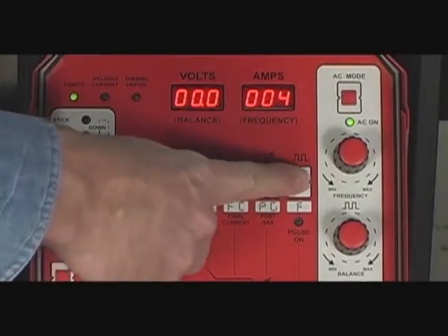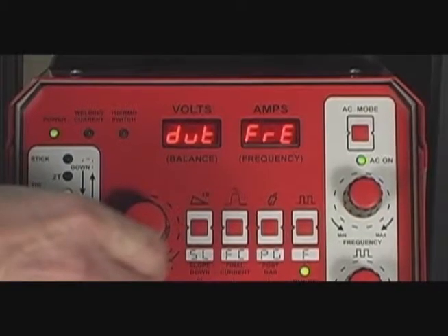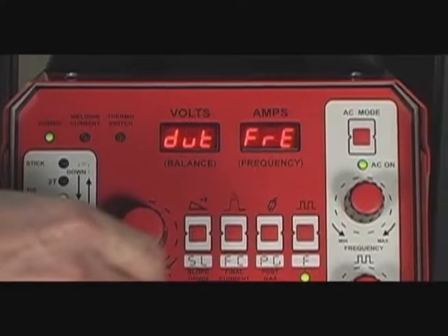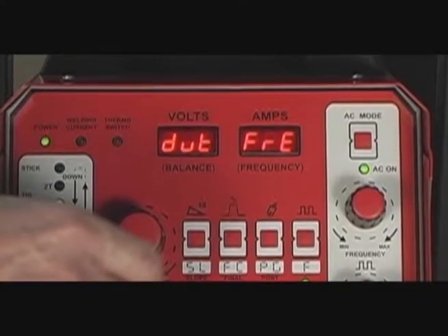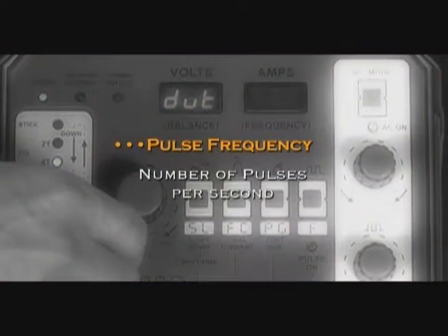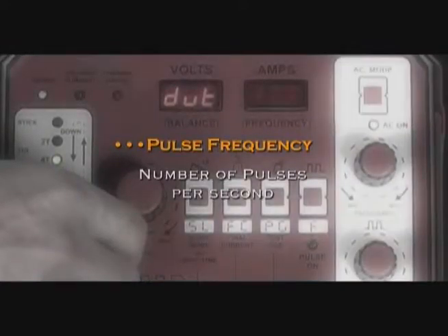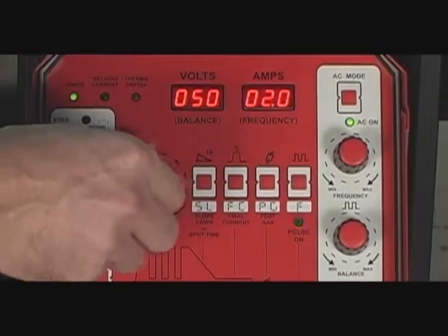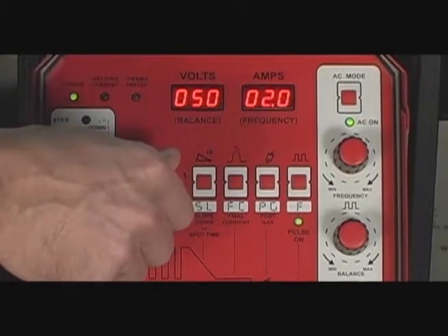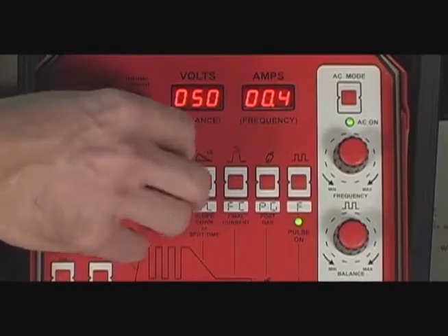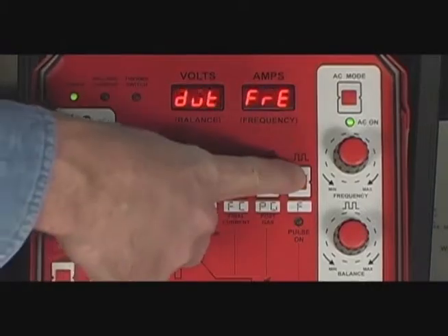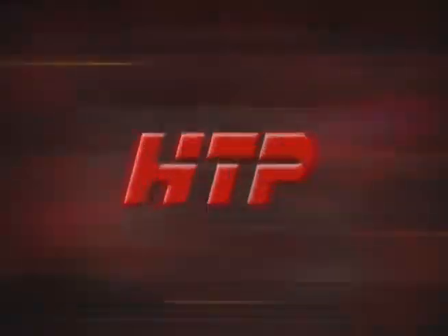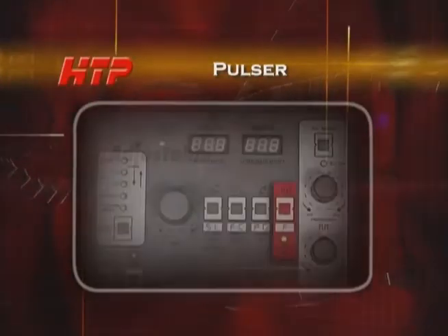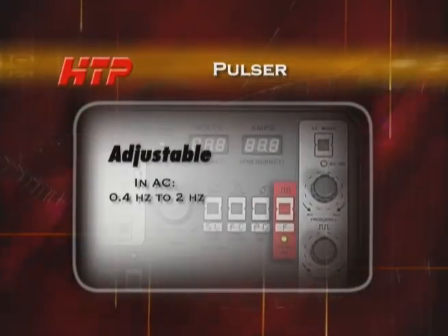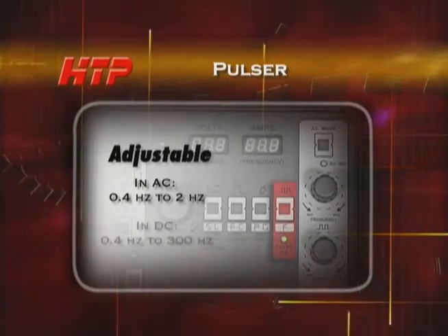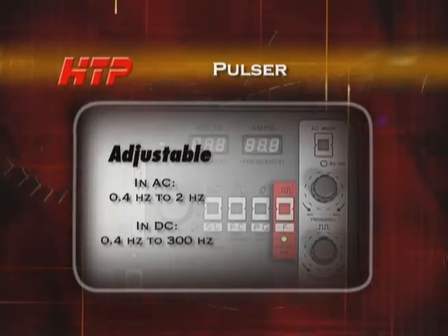To adjust the pulse frequency, depress and release the pulse on button until FRE, which is displayed in the amps display, is flashing. The pulse frequency is the number of pulses per second. While the display is flashing, adjust the amps knob to set the pulse frequency. Once the amps knob is turned, the display will change from FRE to display the frequency in hertz. The frequency can be adjusted from 0.4 of a hertz to 2 hertz in the AC mode and from 0.4 of a hertz to 300 hertz in the DC mode.